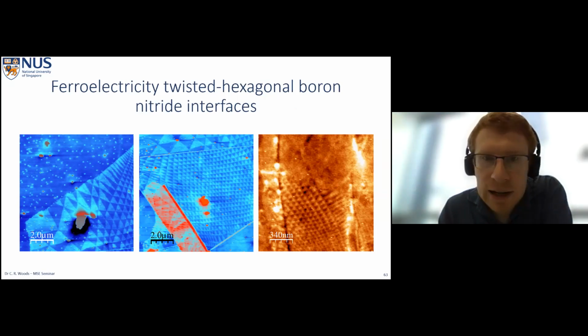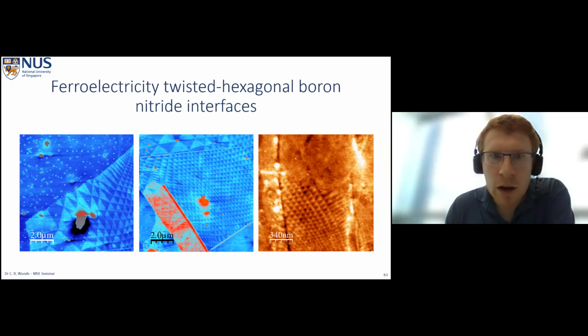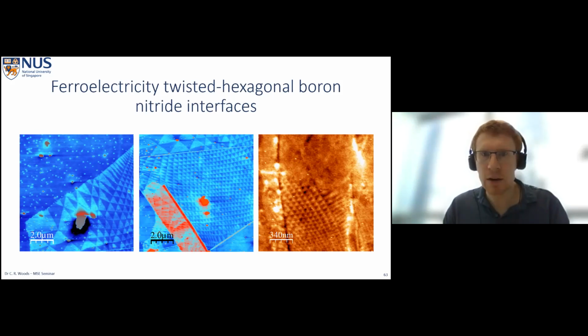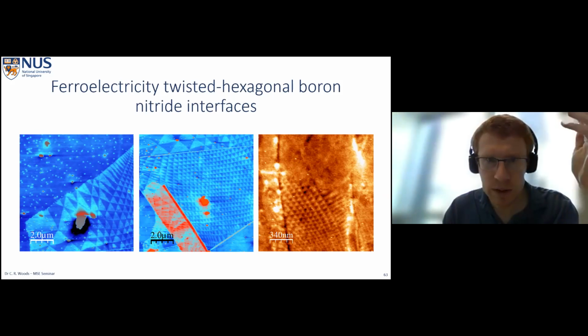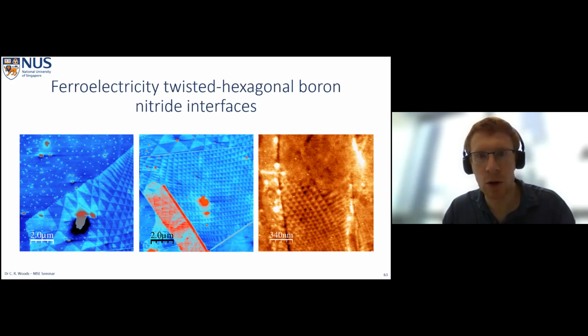So the question is single layer graphene on monolayer boron nitride, I'll assume, because if I put single layer graphene on, say, bulk hexagonal boron nitride, of course, because bulk isn't expected to have piezoelectricity, we wouldn't expect to see piezoelectricity there. So I'll assume the question is single layer graphene on monolayer boron nitride. And do we expect to see piezoelectricity there?